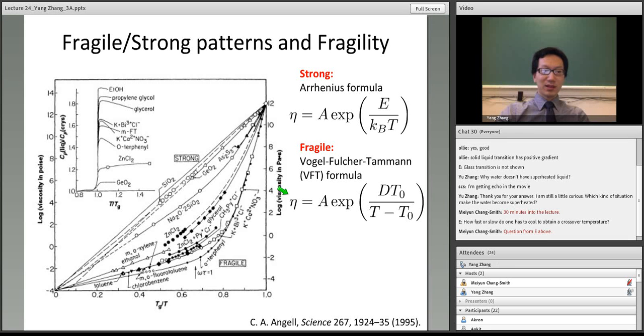Based on this, we can also define so-called fragility. Fragility is basically the slope in this Arrhenius plot at the glass transition temperature. So the slope at this point. It's amazing that for many glass formers, we can define the fragility, and most of them follow these two fragile to strong patterns. But it is still an open question how to explain the fragile and strong behavior, and what molecular architecture or kind of interaction can give rise to this strong or fragile behavior. Most of the strong materials have an open tetrahedral structure, like silicon, silica, germanium. But we still don't really have agreement on how to describe the fragility of materials.